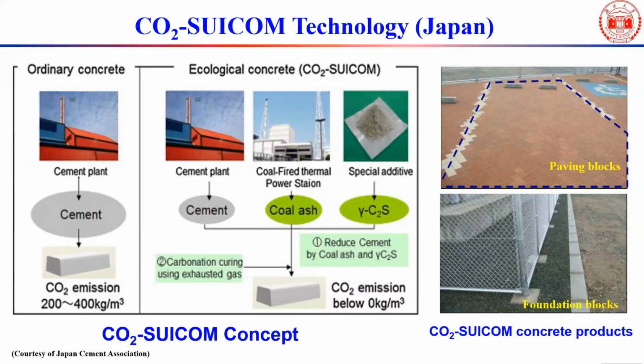Because the gamma dicalcium silicate, as I said, once the carbonation is finished, does not have the potential for further hydration. And coal-fired thermal fly ash, if it's low calcium fly ash, basically acts as a filler. And cement is regular cement. Anyway, they are marketing this technology and they have also done quite a lot of demonstration.